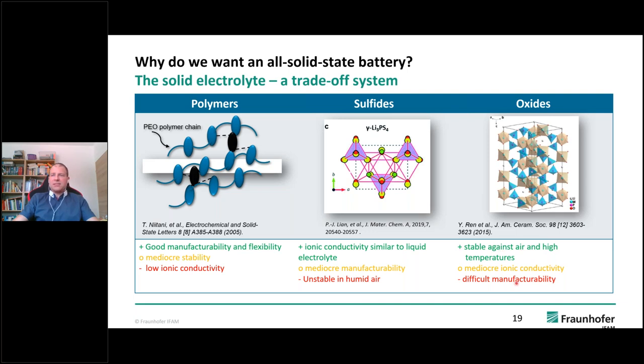But on the other side, the manufacturability for the oxide is very low, because mostly oxides are sintered at very high temperatures. And this means that we have a lot of ions moving around, making it hard to build these cells at large scale and even to achieve a running cell with these materials, because we have problems like moving of different metal ions during the sintering process.